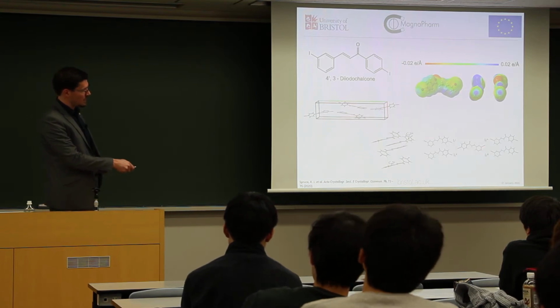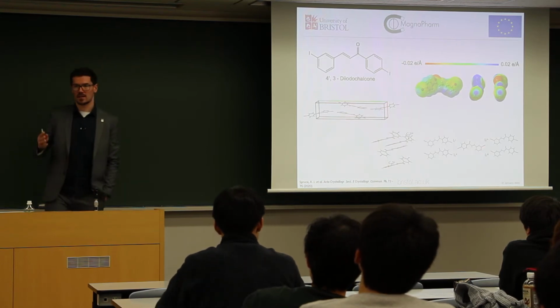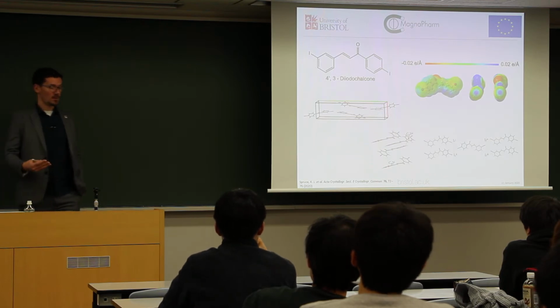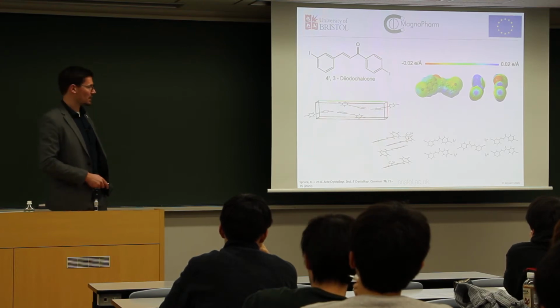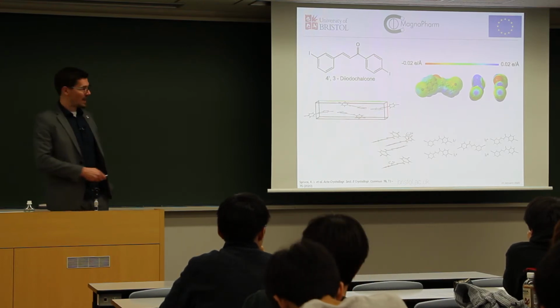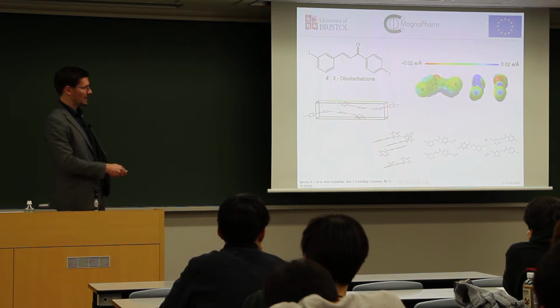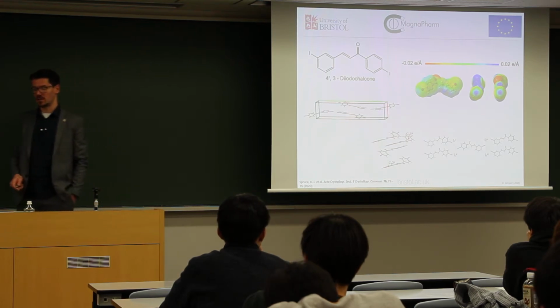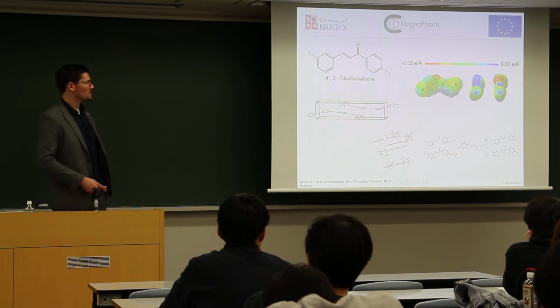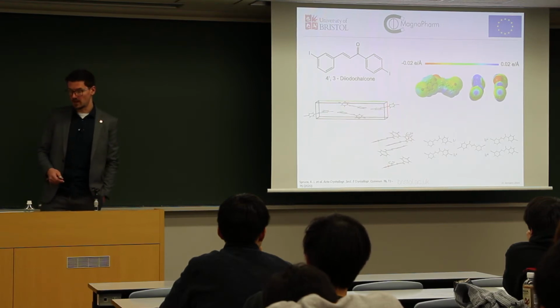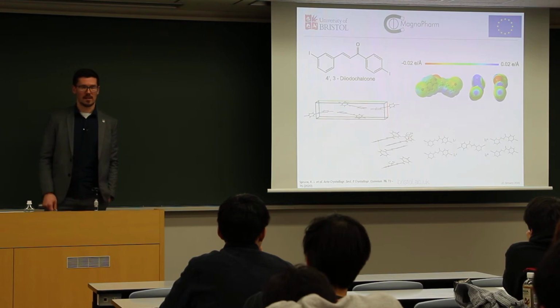These halogen bonds go all the way through the crystal and make these nice iodine channels, which we think might be interesting for conductivity. Lots of delocalized charge moving around. But also in this crystal, what we have are the stacking interactions, the pi stacking dispersion forces that are holding the crystal together and stabilizing it in a third dimension. So this is the sort of thing we're dealing with on a daily basis.